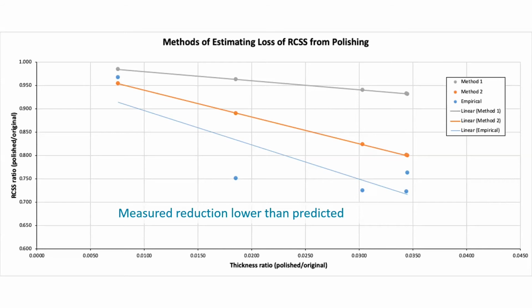And so we said, well, we want to see how this compares. When we actually measured it, we found that our original, when we just barely took anything off, was reasonably close. But we found very quickly, as we continued to remove more glass material, that the RCSS drops significantly faster than even our algebraic attempts predicted. So we know there's more going on here than we can predict right now with our rudimentary attempts at the model.